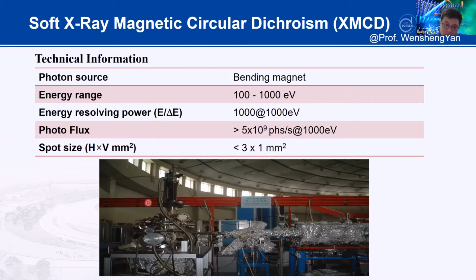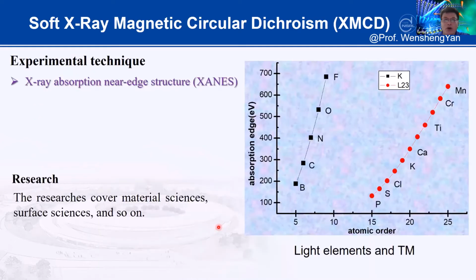This is the real picture of this endstation, as you can see. This is what I very often did: soft X-ray absorption near edge structure at this endstation. As I mentioned, the energy can go from 100 to 1,000 eV, which is very sensitive to light elements, the K-edge of light elements, and also the L-edge of transition metal elements.